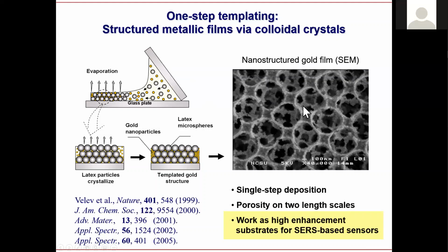So the usefulness of this is that you have a layer of gold, which is very open and has extremely high surface area, and the open area of the gold nanoparticles creates plasmons, as you have heard from different classes, including mine. So this is a gold surface. If you put this in water, you're going to have very high mass transport to a very high surface area of gold.